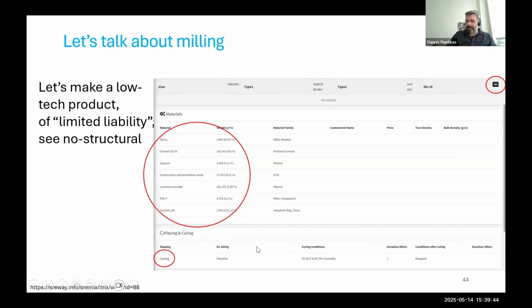Second thing was the milling. Here, interestingly, from a semi-philosophical perspective: most people, when they think milling and building materials, think dry milling. Why would you do that? Because one, it's easy. Two, you wouldn't do wet milling for cement, because the whole idea of cement is that it hydrates, so you don't want water. Three, somehow in the labs, you always have dry milling, or most often dry milling. But if you look into iron ore, wet milling is very, very common, or in fact, the standard. So if you look into the ISA mills, for example, it's about wet milling. So why don't we do wet milling for the slag? Because the slag will not hydrate.